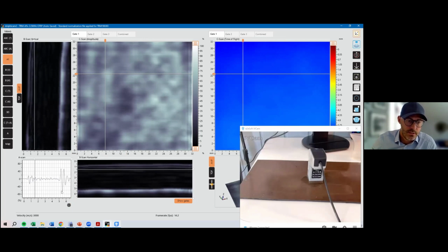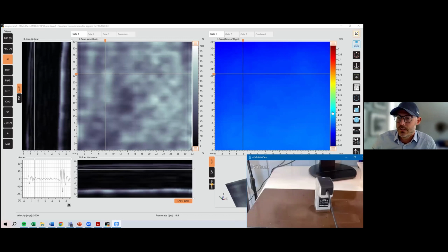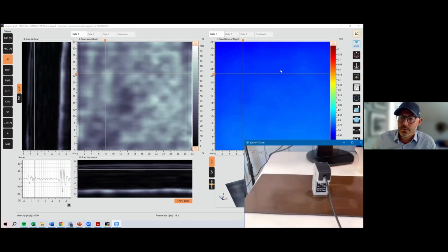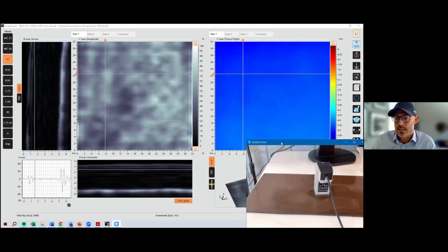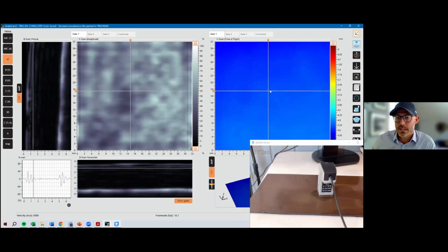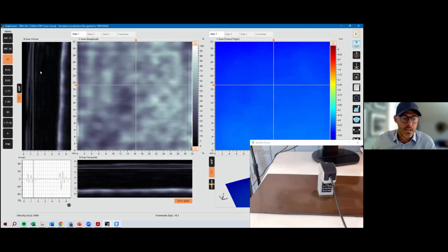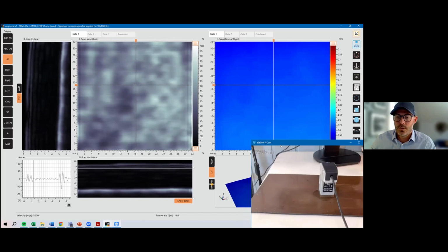So you can see this time here is about between 5 and 5.5 millimeter. And that's also this color scale here, which is the blue one. It's the 5. So I love this blue picture because that's a time of flight. It tells you something about the depth. And then where I slice this image is where I get my B scan here vertically along this side, and we have a B scan horizontally across this side. I'll show you the 3D afterwards.